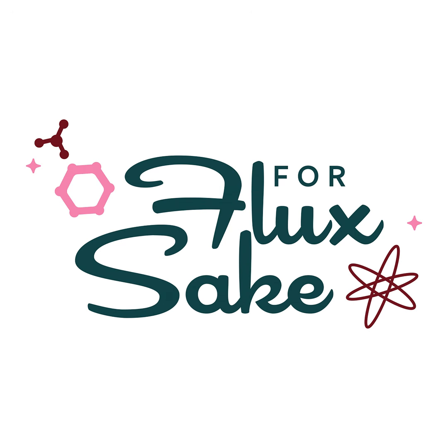Okay. Give us some context. What's the difference between 4 and 5 and 6 and 7? Well, from cone 4 to 5 is 1162 to 1186 C, or 2124 F to 2167 F. So that again is not as big of a gap, but they can be random. The classic one is between cone 10 and 11, which is only 9 degrees Celsius, 2345 to 2361. So that's 16 degrees Fahrenheit. Again, it's because they're measuring temperature and not chemistry.